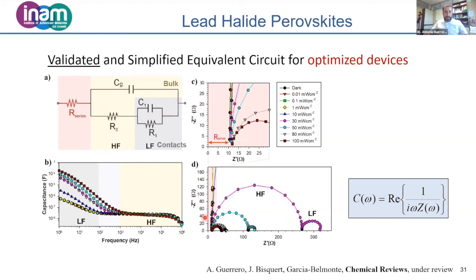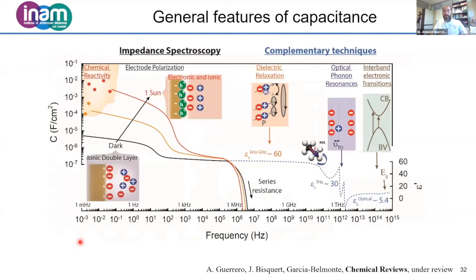As I mentioned, the capacitance and the impedance are related. So this arc shows as a plateau in the high frequency region, and the low frequency arc is related to the contact. Okay, so I will not repeat this many times, but this low frequency arc also shows as a plateau in the low frequency region.